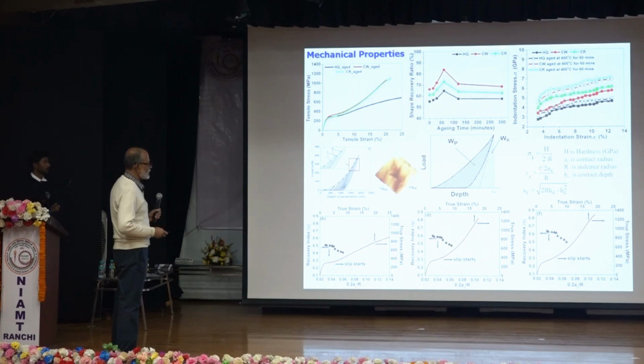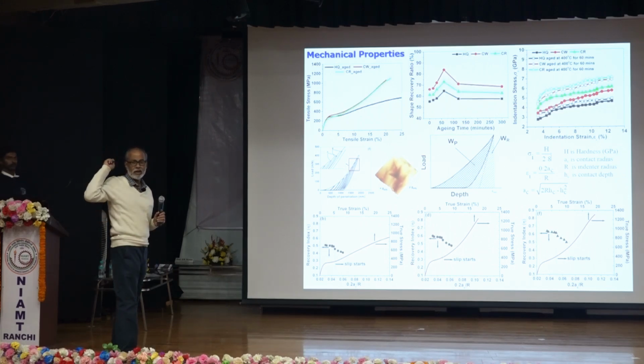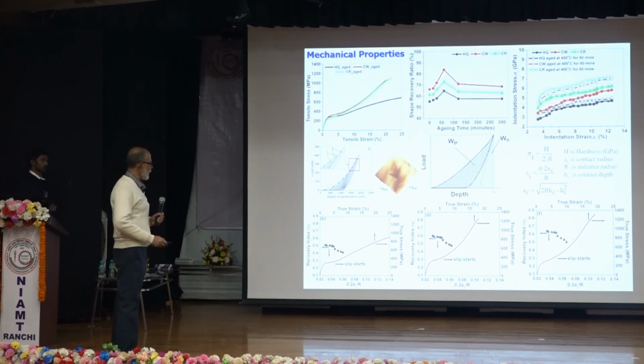Be with me with patience for 1 minute. This is a tensile curve. And from the nanoindentation experiment, we determined a parameter called recovery index, which is nothing but the ratio of the area under the loading curve, that is this total area, and the area under the unloading curve. This ratio determines the recovery of the sample once you withdraw the indenter, right?